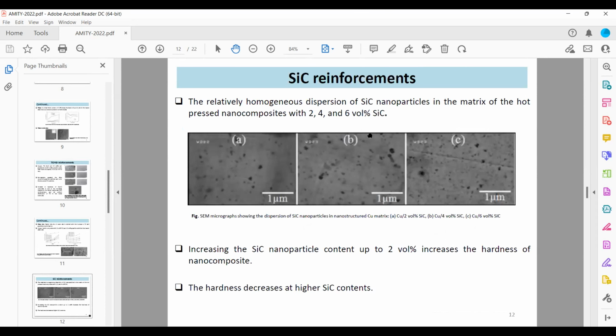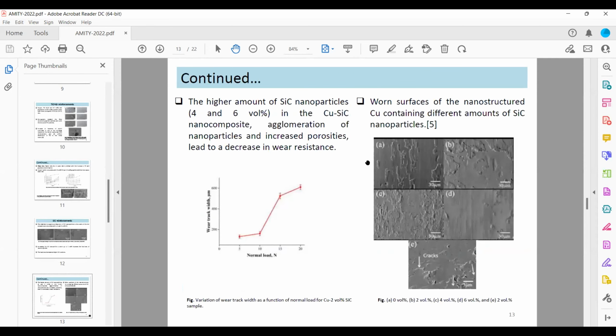Silicon carbide reinforcement. Silicon carbide is usually used when we need to control grain growth, and because it improves the thermal stability of the nanocomposite. The grain size decreases, so it increases the hardness. Now the addition of up to 2% SiC nanoparticles results in an increase in hardness value, because higher SiC will agglomerate and form clusters, which decreases the hardness value.